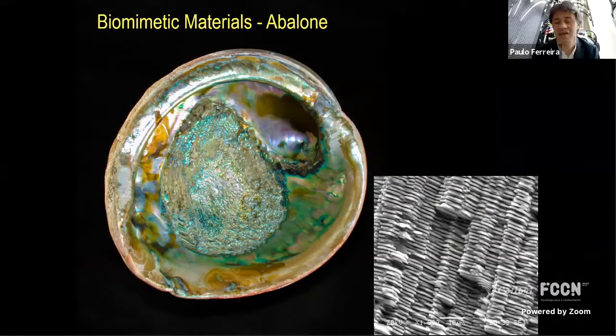The reason is that if you look again at the very small structures, you have this ceramic, calcium carbonate. Basically, you have these layers, as you see here in this image. But what you don't see very well is between the layers, there is a very nanoscale layer of polymer. So if you try to break it, the fracture propagates relatively quickly through the ceramic material, but then encounters this polymer in between the ceramic layers. And of course, it gets deflected. So it's not very easy to propagate the fracture across all these plates, because of this intercalation of polymers in between. This is a very interesting structure that gives this kind of strength that you experience when you are dealing with these things.